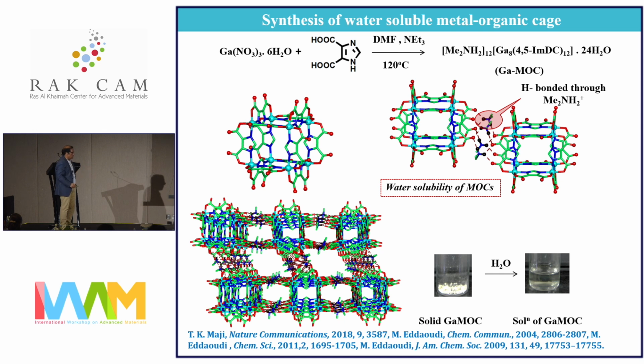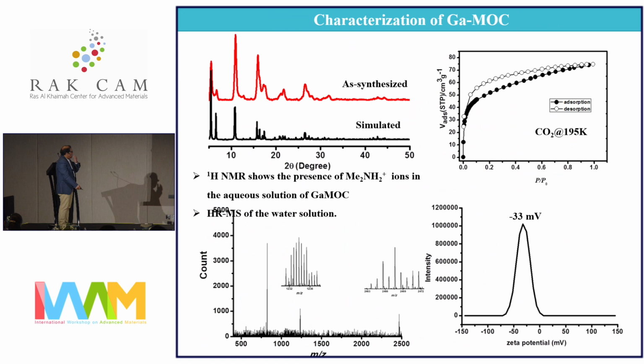This forms a three-dimensional structure. When you dissolve these things in water, it forms a clear solution, like dissolving a metal salt. When we did the HRMS, we found the MOC is stable, and the overall surface charge from the zeta potential is minus 33 millivolts.